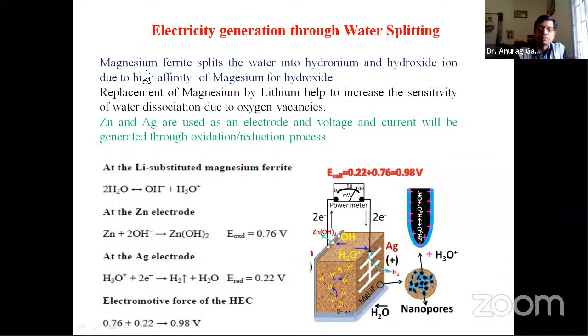What is the material? It is basically magnesium ferrite. You know that ferrite materials are very active, because the iron is present in different valency states in these compounds. That's why in this magnesium ferrite, particularly, we have done doping with lithium. That further accelerates the water splitting process, and it also increases the sensitivity of water dissociation using this compound. So this magnesium ferrite we have doped with lithium.